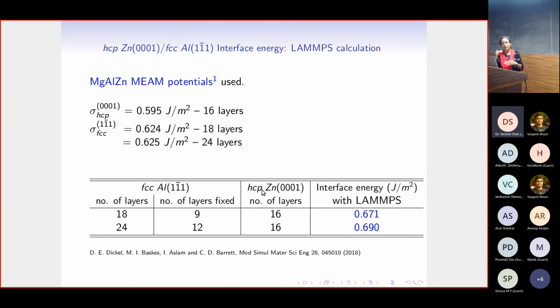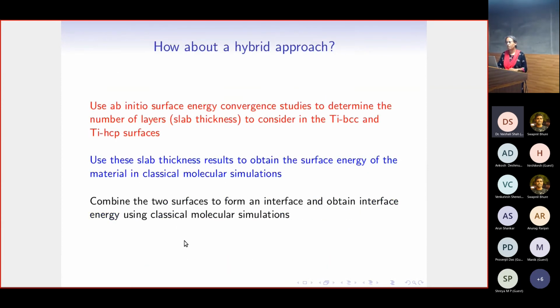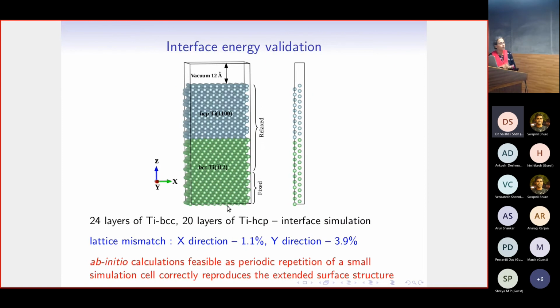And how is the interface energy calculation done? If we are looking at an 18-layer aluminum surface, out of these 18 layers, when we want to get the interface energy, we keep the bottom 9 layers fixed. For the HCP, we are not fixing anything; we allow all the layers to relax. Similarly, if we have a 24-layer thick slab, we fix half the layers. I put this in the slide here. In the interface calculation, we keep a certain number of layers fixed and allow the remaining ones to relax to determine the energy of the interface.